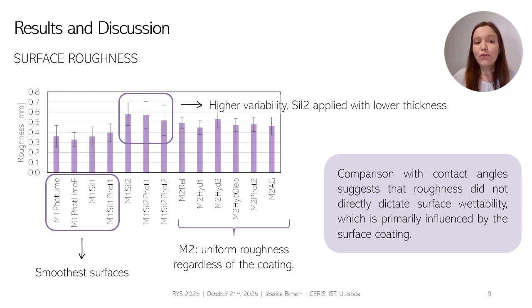For surface roughness, if we look at mortar type 1, in the systems applied with silicate paint 2, we obtained the higher variability between the measurements. This was because silicate paint 2 was applied with a lower thickness than the lime-based photocatalytic paint and silicate paint 1. These two paints led to smoother surfaces in M1. For M2, we obtained a uniform roughness regardless of the coating type. This indicates that the mortar itself or the different types of paints were the main responsible for surface roughness instead of the protective coatings. Comparing this with contact angles, we saw that roughness did not directly dictate surface wettability, which was, on the other hand, primarily influenced by the protective surface coatings.